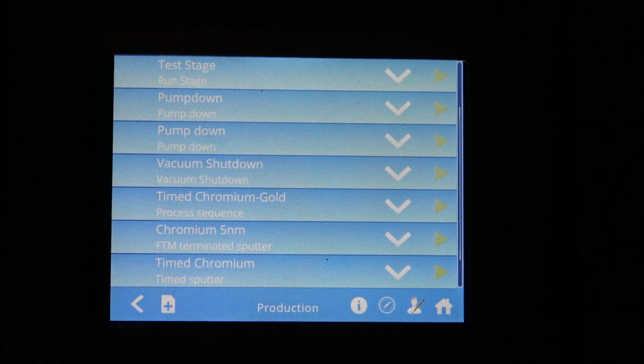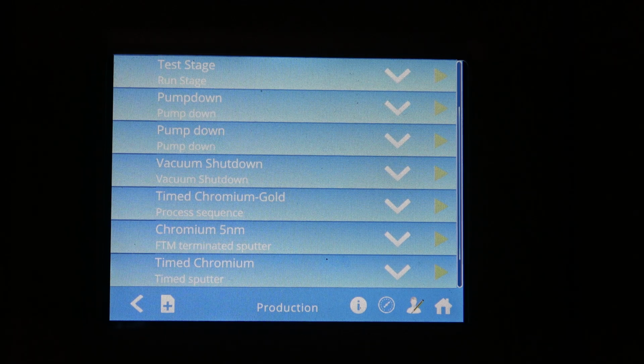If you're sputtering oxidizing metals like chromium, titanium, aluminum, you want to keep water vapor and oxygen out of there, because this causes oxides to form on the surface of the target, which are very difficult to sputter through initially, and will contaminate your sample to some degree. So we want to keep those out.